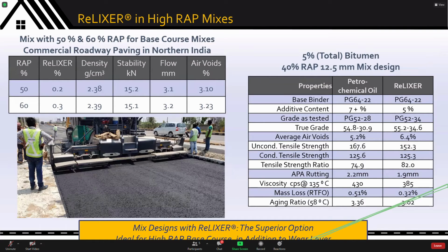Some case studies, I'll start with some case studies from around the globe. In India, there is a rich tradition of high RAP base course mixes using rejuvenation. Here you can see 50 and 60% RAP being used in base courses with rejuvenation. And they were using stability and flow as their spec parameters. Here you can see a case of a 40% RAP mix, 5% total bitumen, comparing two cases, a petrochemical rejuvenator and ReLIXER rejuvenator. And what you can see is the dramatic improvement in long-term properties, in addition to the dosage efficiency of ReLIXER over petrochemical oils and the improvement in low temperature properties.